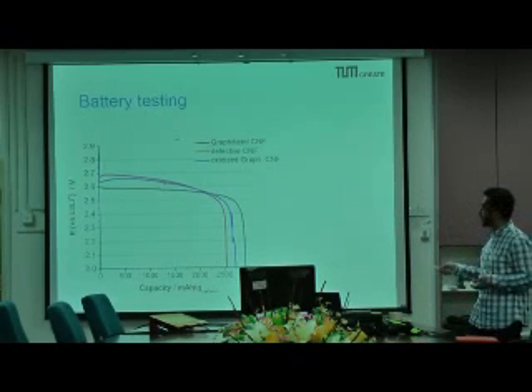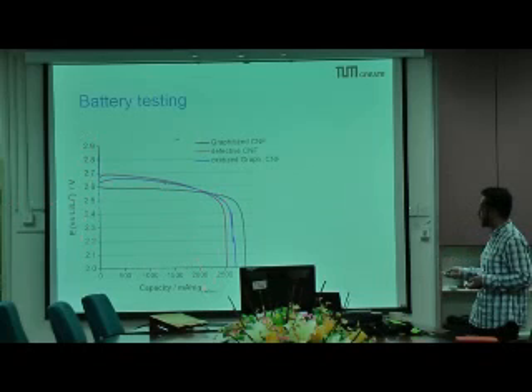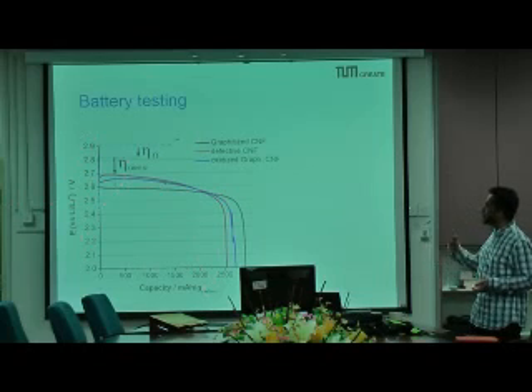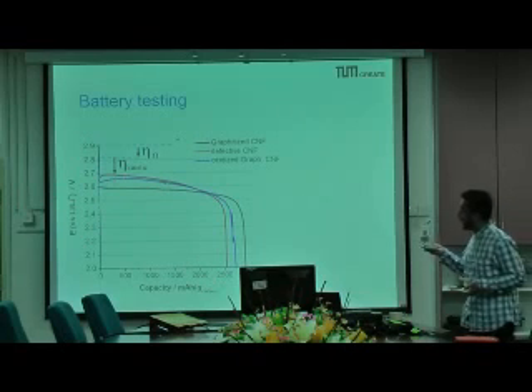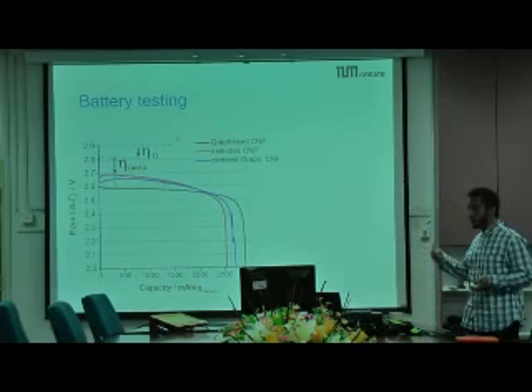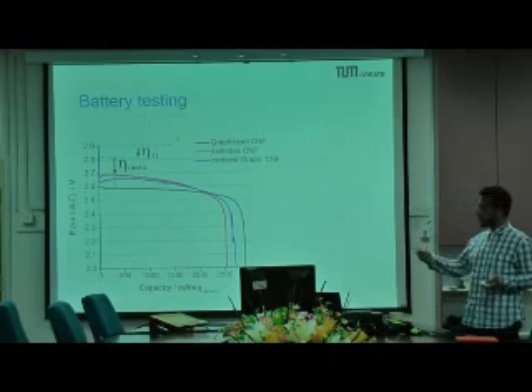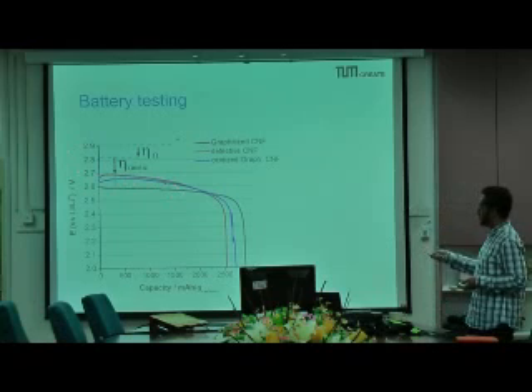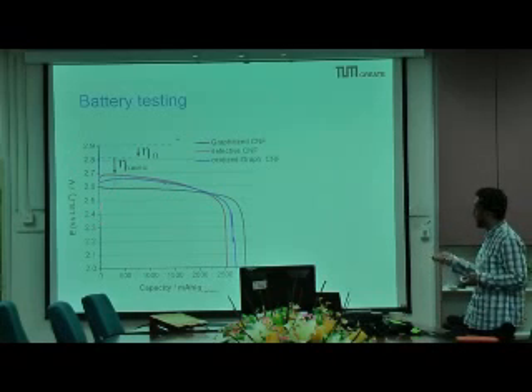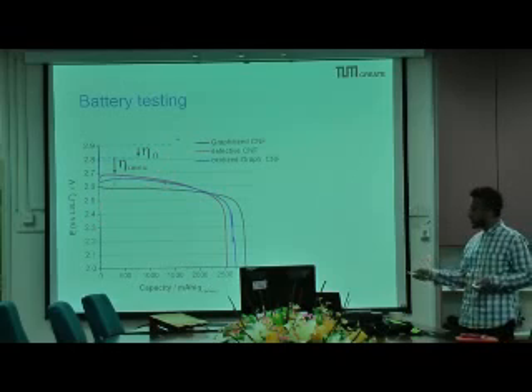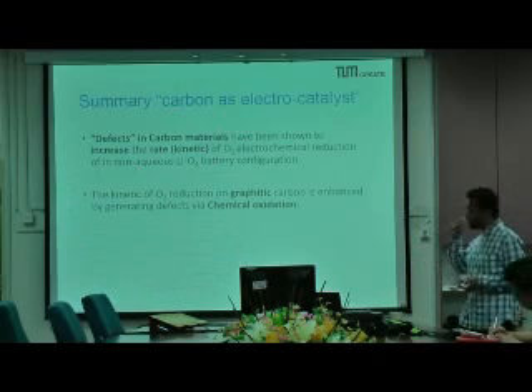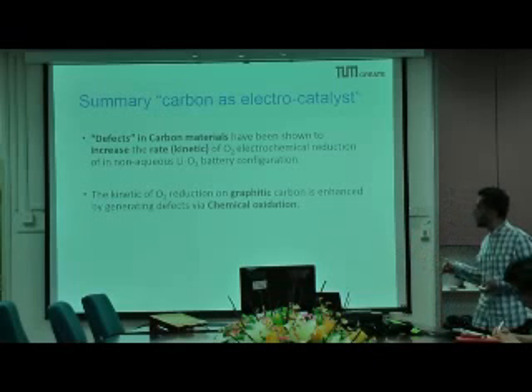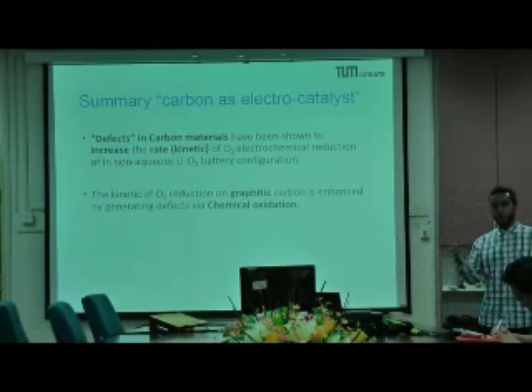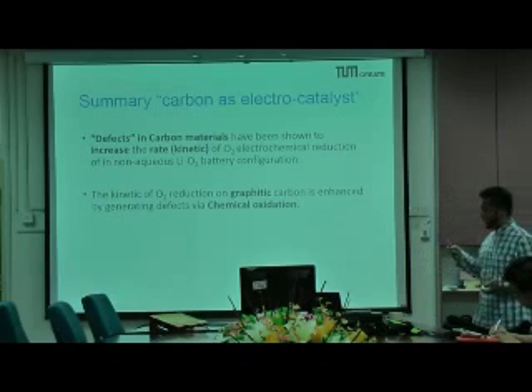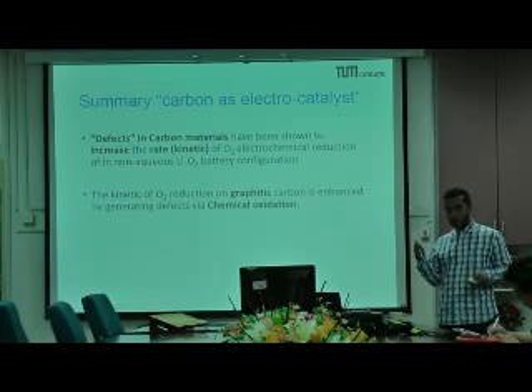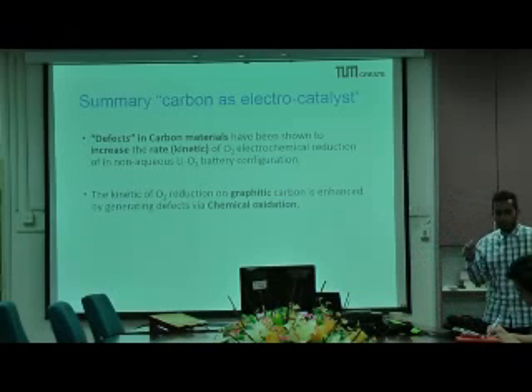So, using this material in a typical battery configuration, you see a discharge curve showing that when you introduce defects into this material, the kinetic barrier in this reaction decreases. That's why you have a higher voltage, improving the reaction kinetics. Of course, as this is the same configuration, the IR drop is similar. So the second summary is that defects in graphitic material increase the rate of oxygen reduction for lithium oxygen batteries, and you can improve the kinetics in graphitic material by introducing some amount of defects.